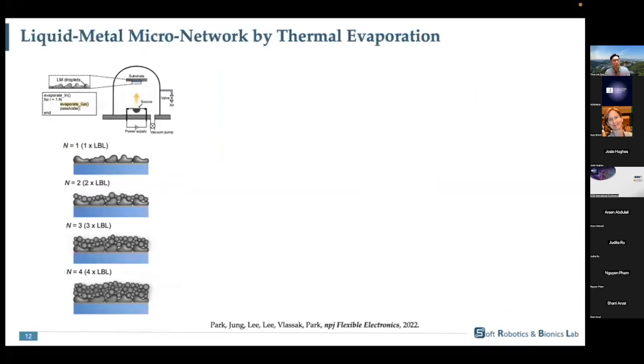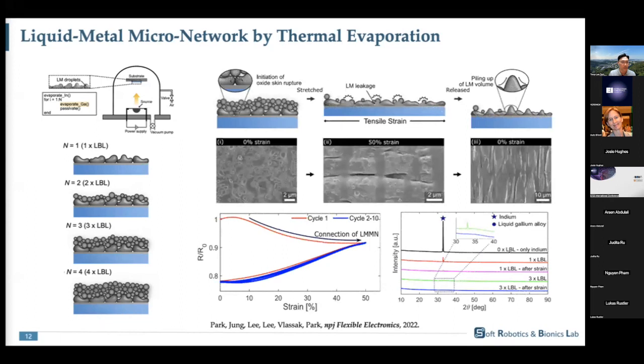Another manufacturing method we were looking at is thin film coating, which is used in the semiconductor fabrication area. In this method, we use thermal evaporation, and we deposit very thin layers of indium and gallium multiple times. But once you deposit these multiple layers of gallium, because of the oxide skin, they are not really conductive. But if you stretch it for the first time, the oxide skin breaks, and then there are leakages of liquid metal coming out, and then they construct 3-dimensional microstructures and a micro conductive network.